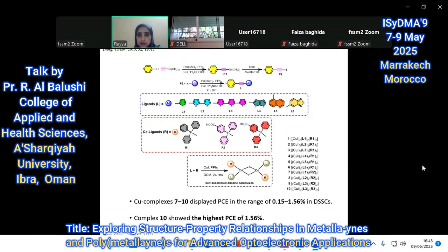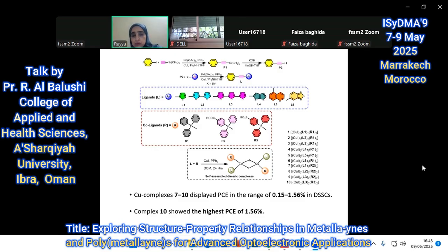So we replaced the ferrocene with phenylphosphine groups, with different phosphine ligands, and we found that the materials have good solubility, so we could process and characterize them. As is clear in the slide, we used different types of ligands and phosphine salts, and the copper complexes 7 to 10, with different ligands, displayed power conversion efficiency in the range of 0.15 to 1.56, where complex 10, which contains the sulfonic phosphine, has the highest power conversion efficiency, 1.56. So this opens a window to further different copper complexes. We are also still working on new materials with copper salts.